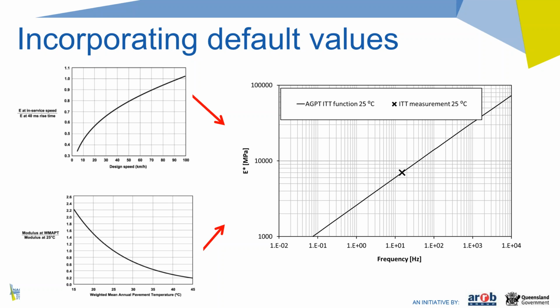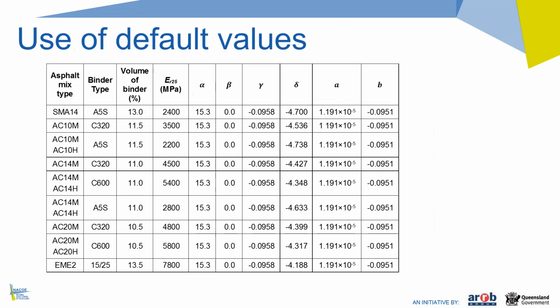Obviously, the results you're going to get are not more accurate than in the current Ostro's method. The main difference is that you can consistently use master curves instead of the resilient modulus results. So this is a table in the design supplement showing you the default master curve parameters for the different mixes, typical mixes used by TMR, as shown in the left column, and it gives you default master curve values for this. But obviously, this will just end up with the normal Ostro's relationship, as I've shown on the previous slide. But it can be used with default values as well.